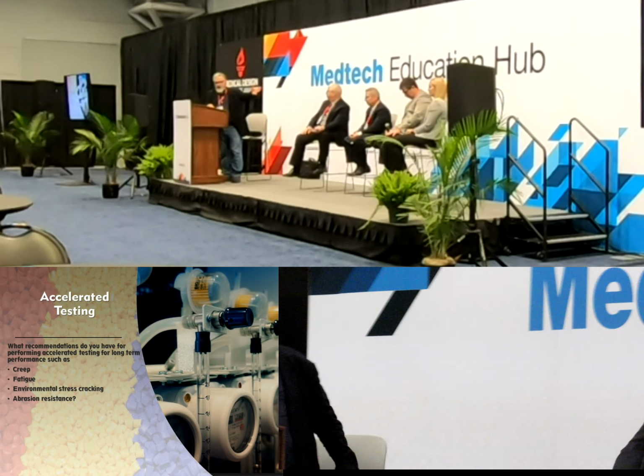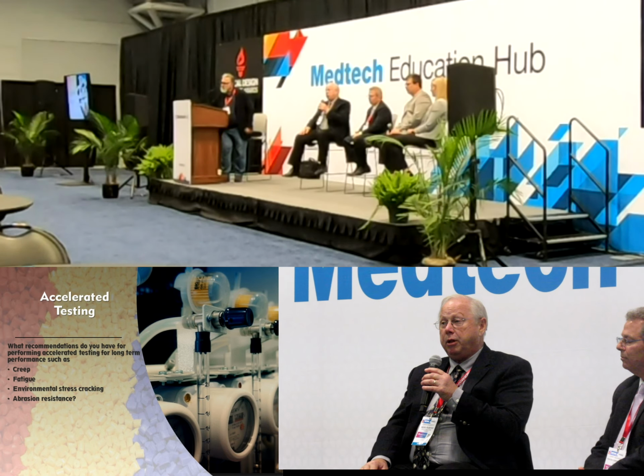I'll start off with Ed. It's a big question, and we could spend hours on it. I will very quickly say there are some applications where you can get a pretty decent idea, like DMA analysis for creep resistance. Basically you can project out 2 or 3 years based on the DMA analysis, whether or not the material will creep. You can also do thermal testing, where you're elevating the temperature to see whether or not the product is going to fail in time. You certainly can do physical testing, like if you're dealing with a living hinge. You set up a fixture that pushes the part into the function that you're going to apply in real life, to try and simulate what it's going to do in the application.